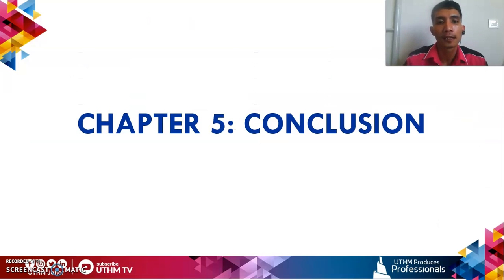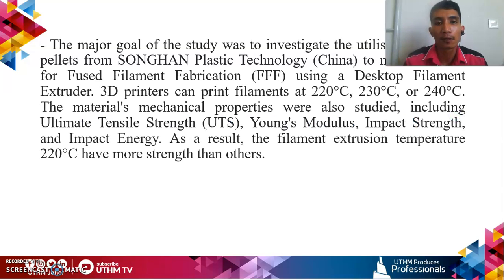Chapter 5, Conclusion. The major goal of the study was to investigate the utilization of ABS pellets from Songhan Plastic Technology in China to make filament for fused filament fabrication using a desktop filament extruder machine. 3D printers can print filaments at 220 Celsius, 230 Celsius, or 240 Celsius. The material's mechanical properties were also studied, including ultimate tensile strength, Young modulus, impact strength, and impact energy. As a result, the filament extrusion temperature 220 Celsius has more strength than the others.